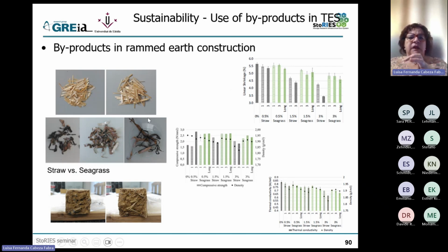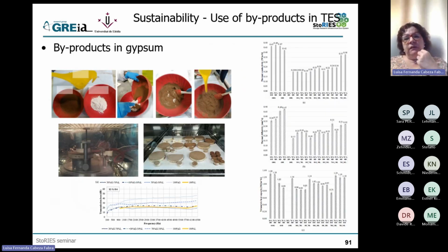This is very similar, but in this case, the waste we were using, which is the picture with this seagrass, is waste from the sea. This seagrass is an algae that ends up on the beaches, and that the municipalities have to take out so that when we want to go to the beach for a sunbath, the beaches are clean. Again, a waste that we were trying to add in our construction system to give this thermal inertia effect. We have used PCM in gypsum. In this case, we were using PCM and also lignin, which is another byproduct from the industry. In this case, it is the biogas production industry. They have a lot of lignin.